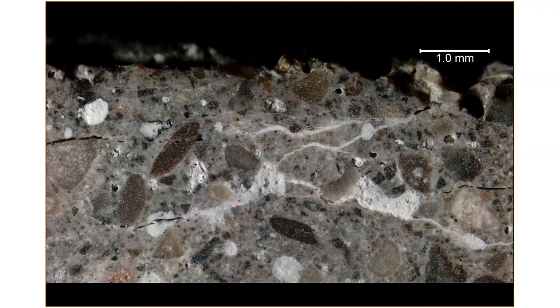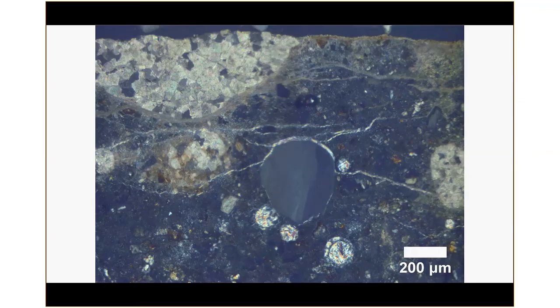When we make a thin section, which is a glass slide that has a very, very thin slice of this concrete on it, basically what we do is we saw cut and lap another section. We epoxy impregnate it. We glue it to a glass slide. We then cut it off very thin, grind it down very much thinner, and polish it. And we put this under a polarizing light microscope or a petrographic microscope, which passes light through the thin section.